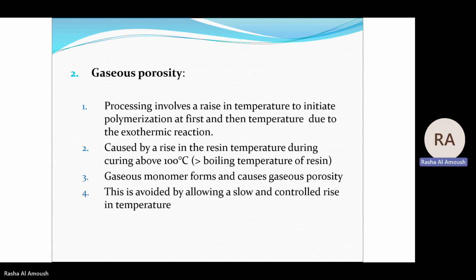The gaseous porosities usually occur because processing, as we said, involves a rise in the temperature to initiate polymerization at first, and then a further temperature increase due to the exothermic reaction. The rise in the temperature above 100 Celsius, which is the boiling temperature of the resin, will lead to gaseous porosity. They will form in the thickest part usually of the dentures. This can be avoided by allowing a slow and controlled rise in the temperature, so that we avoid rising the temperature above or near the boiling temperature of the resin.